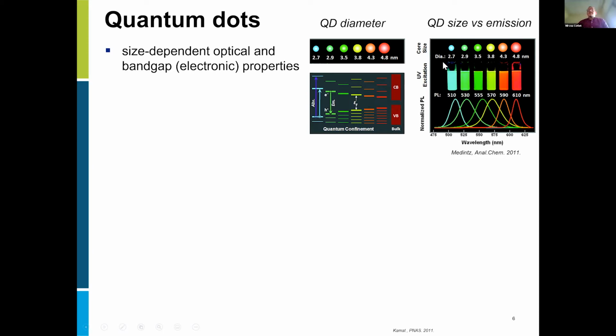The effect on the optical properties is, if we look at these cuvettes here, where we have these quantum dots dissolved in some solution and irradiated with UV excitation, a changing color with a changing size. So going from large quantum dots, we see the color change from red all the way to blue and cyan. Now you have a nanomaterial of basically the same composition, but through size, you can control very well the optical and electronic properties. The first thing that comes to mind is that I have the same type of material, which I can synthesize, control the size, and create a variety of emitters out of this material.